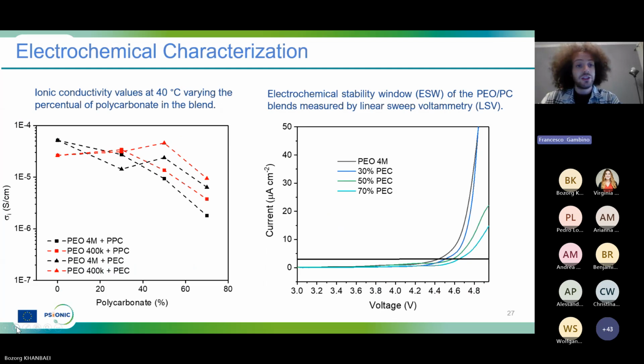After physical characterization, we also evaluated the electrochemical properties of our membranes, starting with the ionic conductivity. Despite both polycarbonates have very low ionic conductivity, around 10 to -9 for PEC and 10 to -10 for PPC, when they are added to the PEO membrane, they cause an improvement in the ionic conductivity. This is caused by the decrease of the crystallinity induced by the addition of this polycarbonate. We compared the conductivity at 40 degrees of all membranes, reaching a maximum at 4.6 per 10⁻⁵ Siemens per centimeter for the formulation of PEO 400,000 mixed with 50% of PEC. And after 50% addition of polycarbonate, there is a detrimental effect induced by this polycarbonate. In fact, there is a drop in the ionic conductivity.